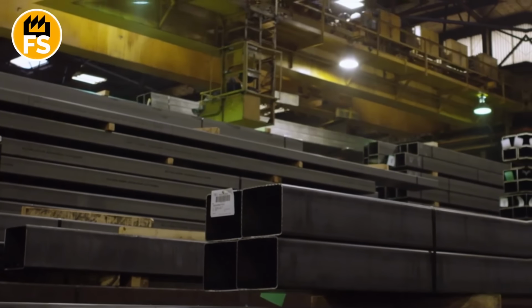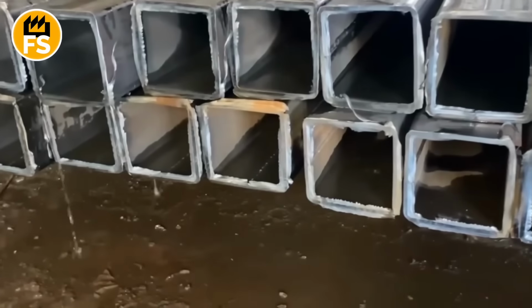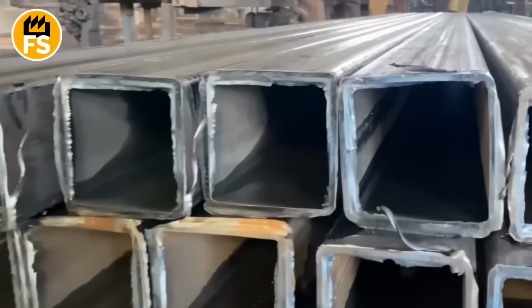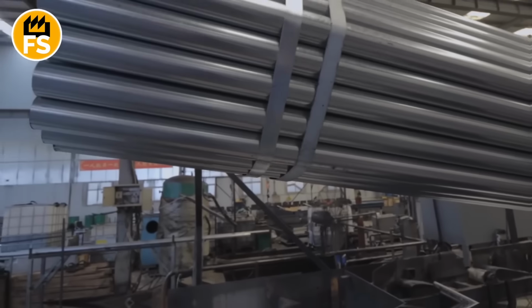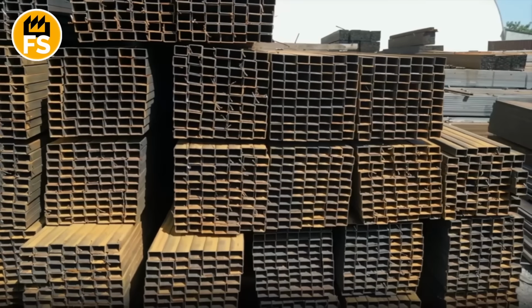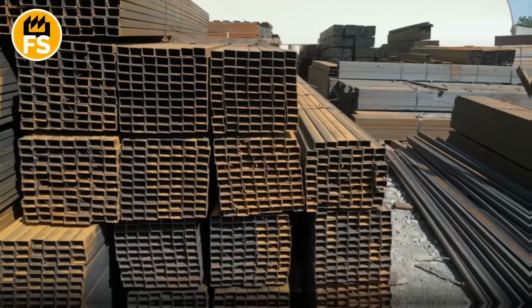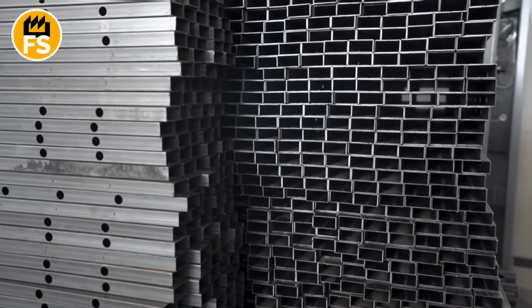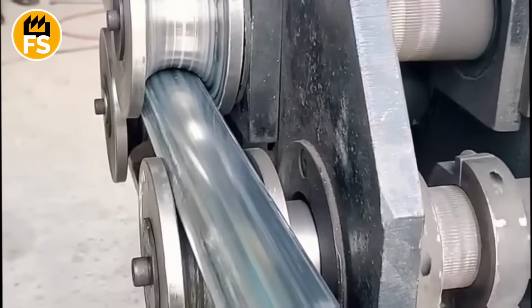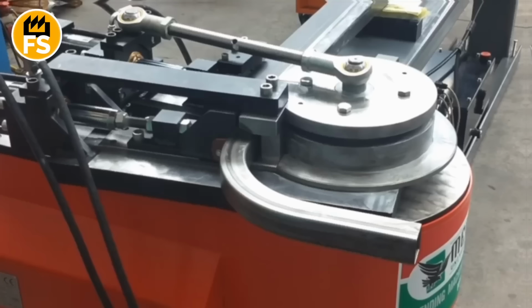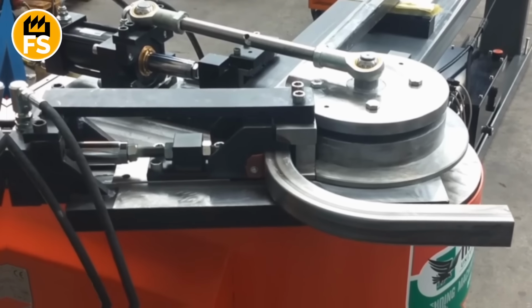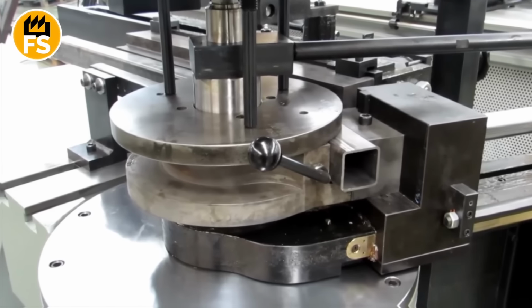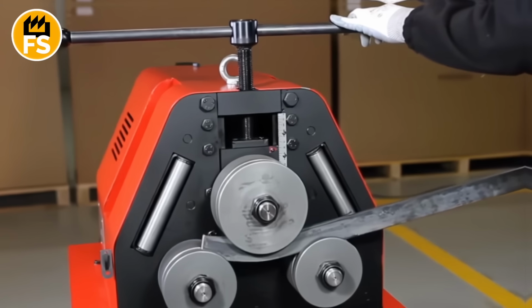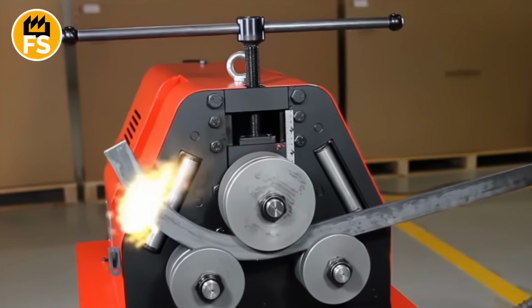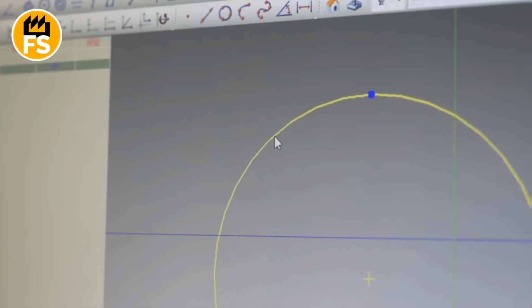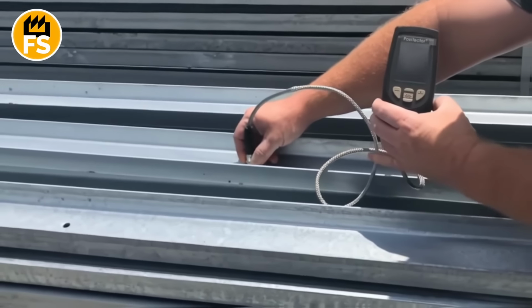The foundation of the Diagrid is hollow structural steel sections, HSS, ranging from 12¼ to 24 inches in diameter. These aren't straight pipes. Many of them had to be curved to follow the shape of the sphere. And not just curved, each beam had its own unique radius of curvature. At the factory here, they used specialized equipment for bending pipes of this diameter. It's not a fast process. Each beam is calculated, loaded into a bending press, and slowly, in a controlled manner, formed into the required arc. Then, inspection. Laser scanning confirms that the curvature matches the digital model to within a fraction of an inch.